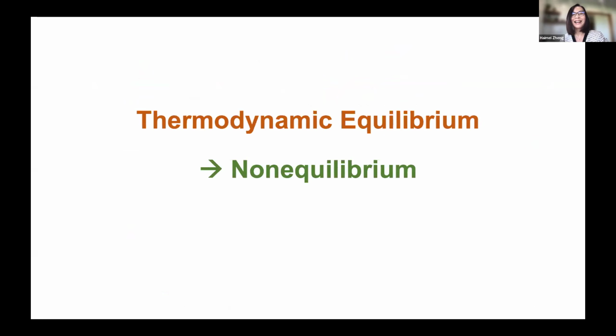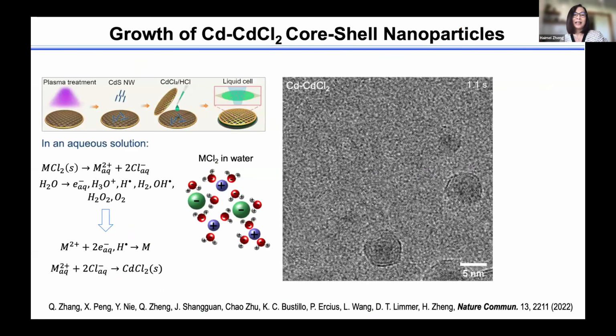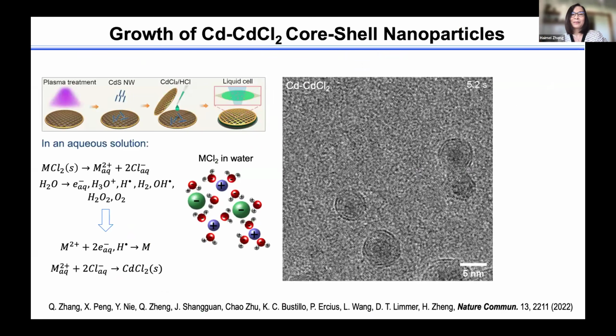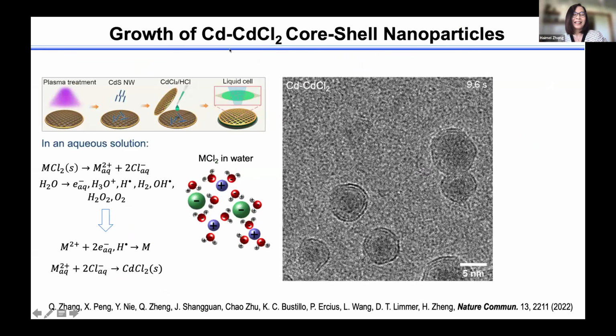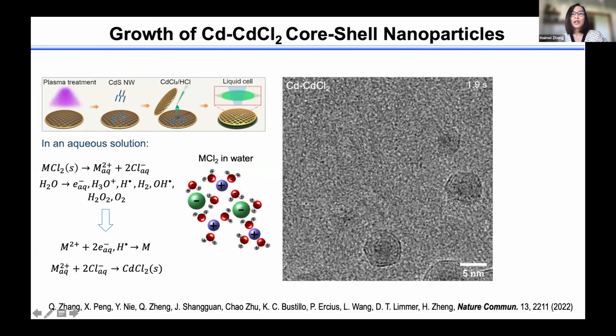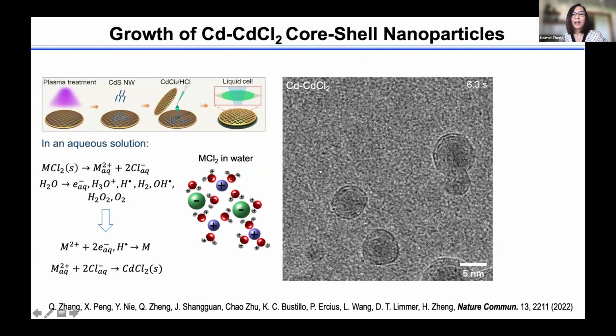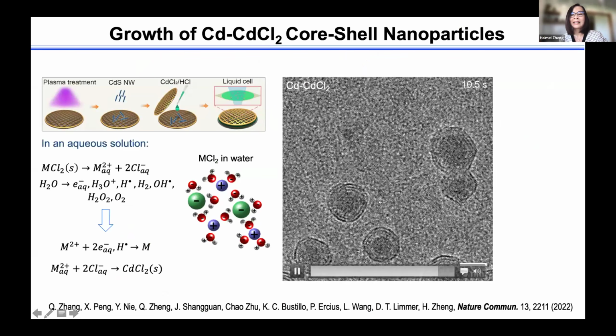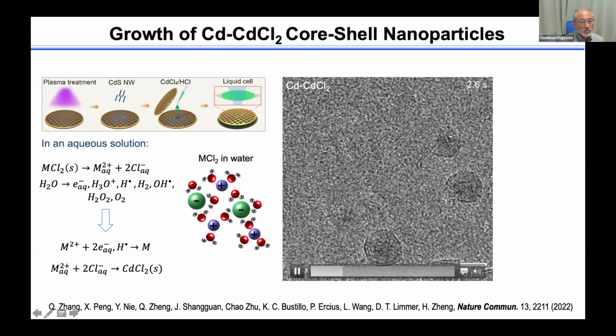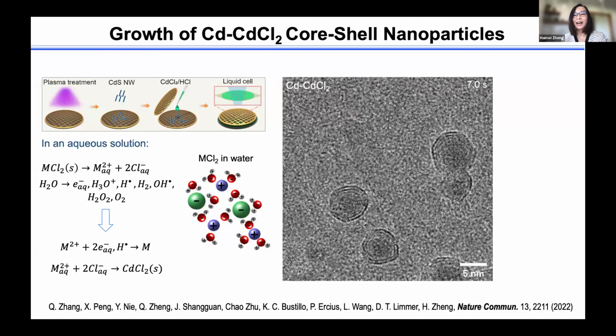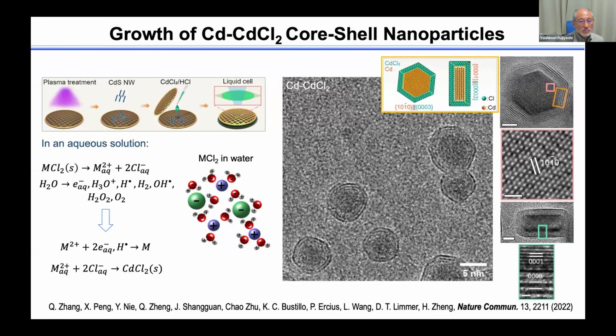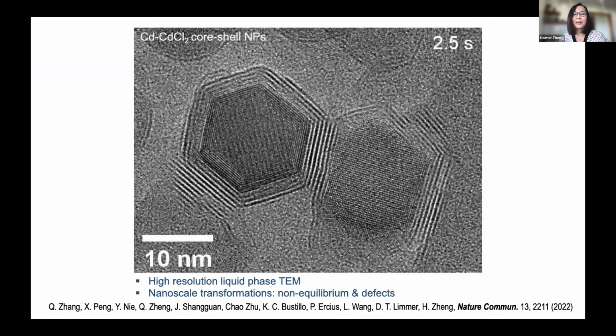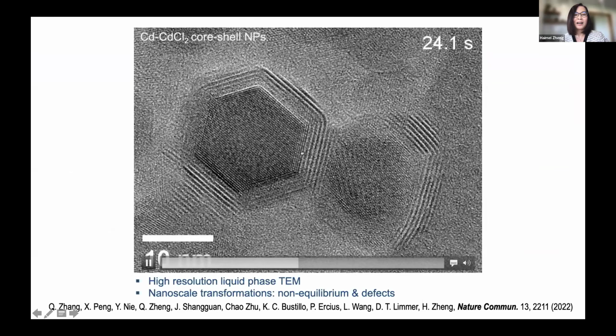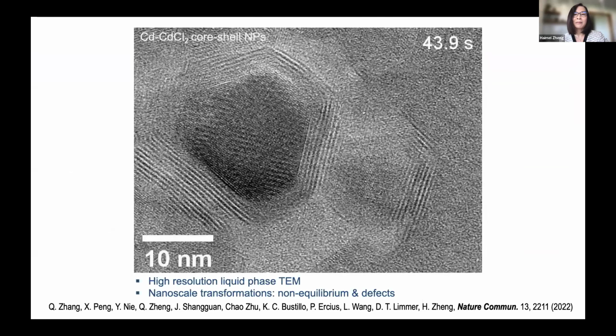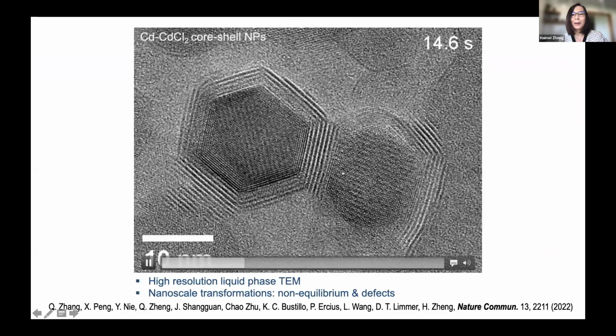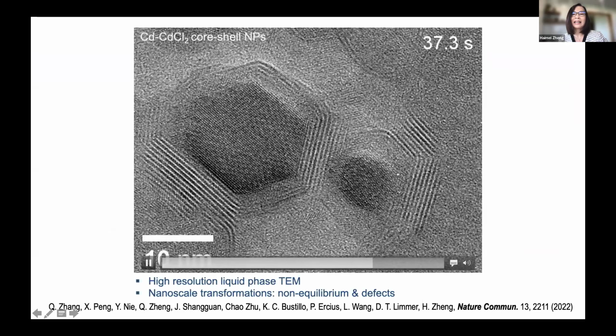However, later we found we have the opportunity to look at more, mostly with the increased resolution. We look at much more details, and here is an example on the growth of core shell nanoparticle of cadmium chloride. And we again use molecular precursor, and we look at these adjacent particles. We found very interestingly, this type of growth, as you see here, they form this 2D nanoplate. And we found this nanoparticle growing completely mediated by defects. What I'm going to show you next is this big particle dissolve because it has an incomplete shell.